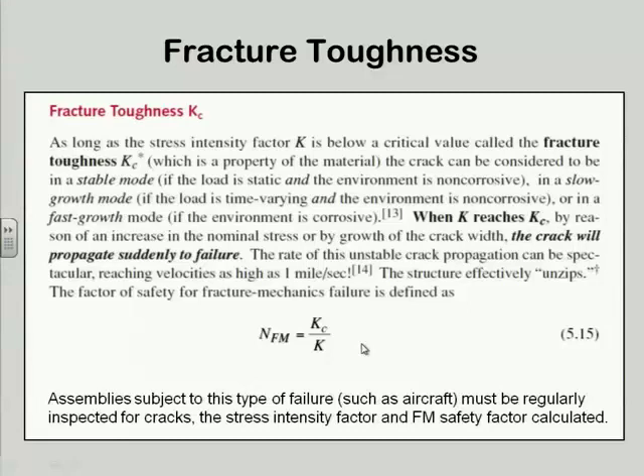Every 1,000 hours, that plane has to be brought into the shop, and certified aircraft mechanics go through it, and they're supposed to X-ray, inspect, crawl into the wings, look for cracks, measure the cracks. They have formulas to apply them to, and you take the crack length, and you calculate these numbers, and you see how close you are to failure, and if you get within the bad zone, you're required to take that airplane out of service and either replace the part or do some kind of repair, okay?